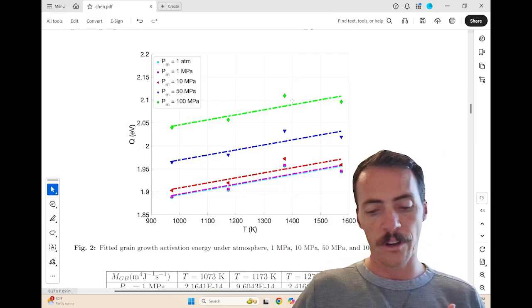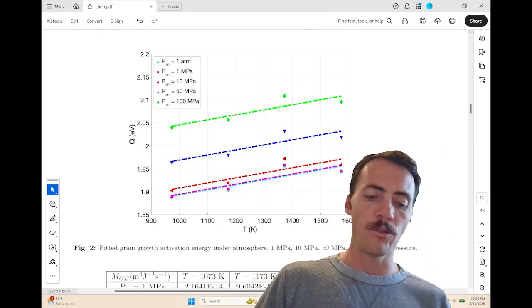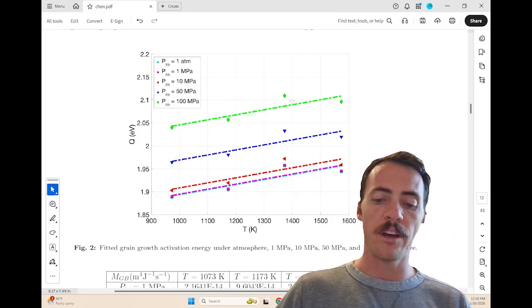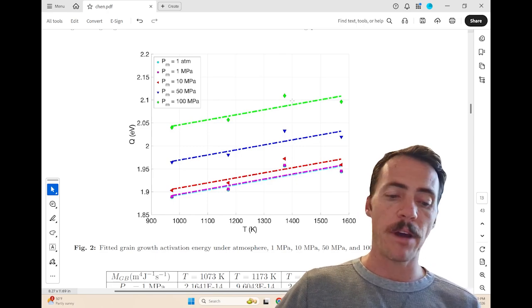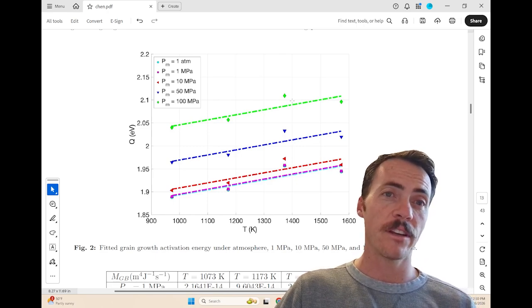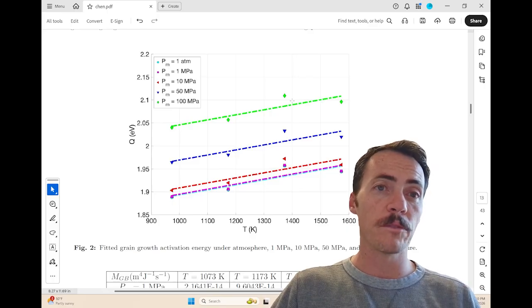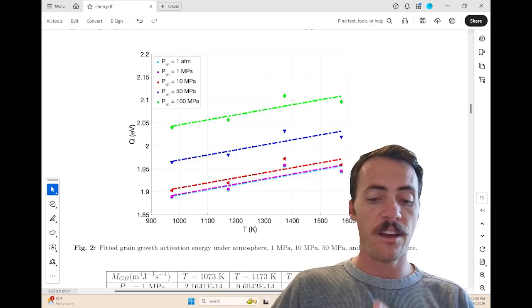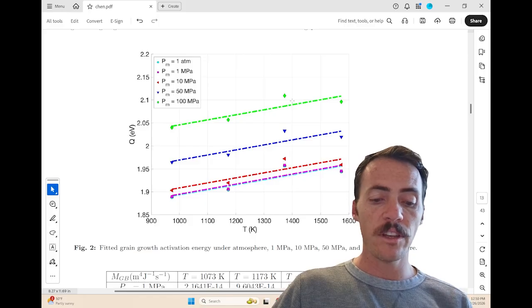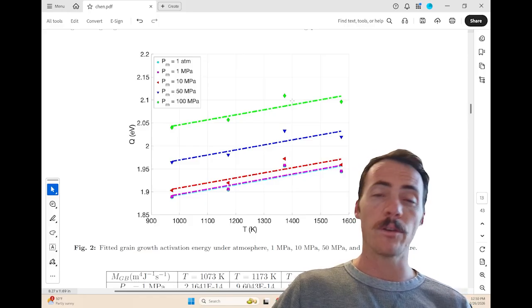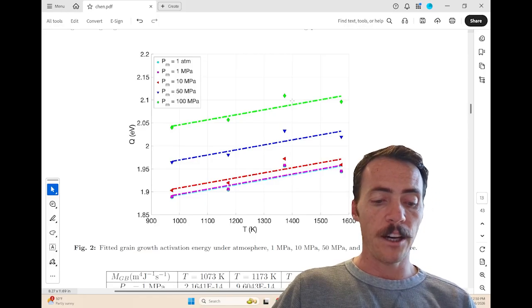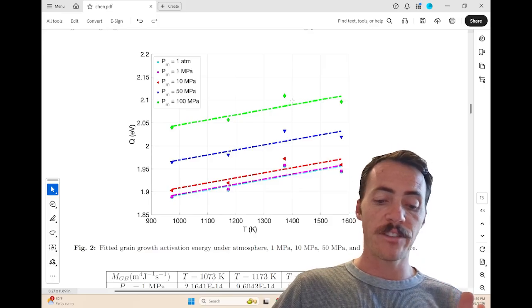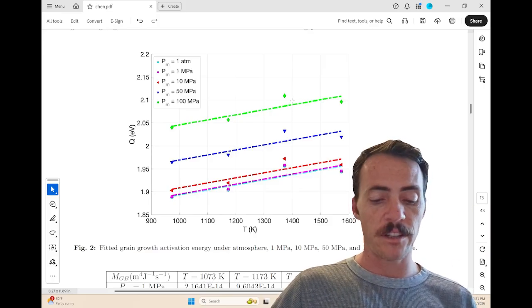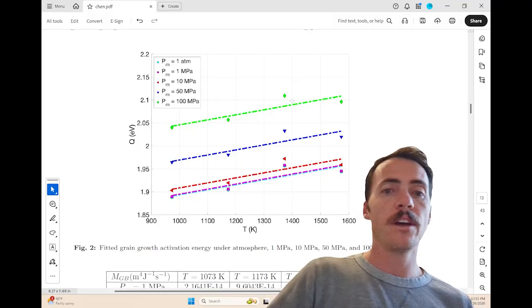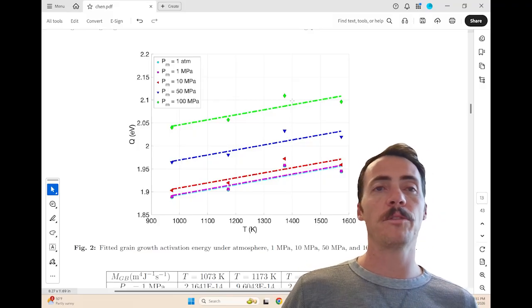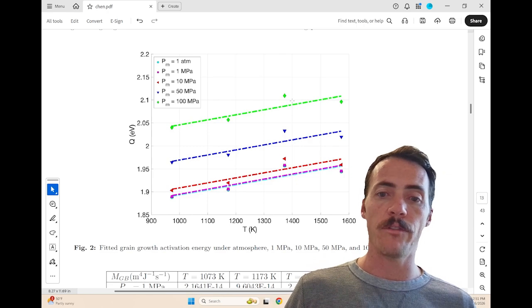If you look at some of the results here, at 1373 Kelvin, as you increase from 1 MPa to 100 MPa, this leads to a reduction in the grain boundary mobility of more than 70%. So if the grain boundaries are less mobile, then they don't grow as much. If they don't grow as much, then in that condition at 1373, you see a 5.7% increase in the predicted yield strength. Pretty big deal. If you do that at 1273, that strength benefit climbs to 7.6%. So this is a definite way where you can control that trade-off between strengthening and reduction of the internal porosity.